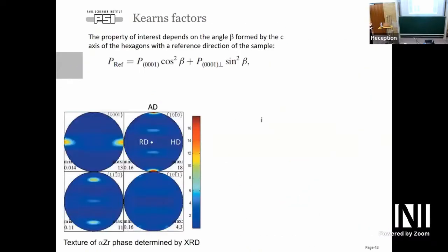So in order to start with this, we decided to start with hexagonal materials. Why? Because it's easier to perform the deconvolution, because it's easier to spot the linearly independent functions that we need. So, did you say hexagonal material? Yes, this is an HCP material. It's a symmetric map with HCP structure. And in that case, the volume is smaller. Exactly. So we require fewer Fourier coefficient components to describe the material. That was why we chose to start with it.